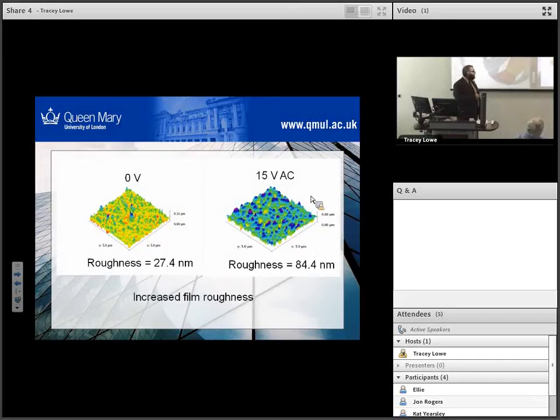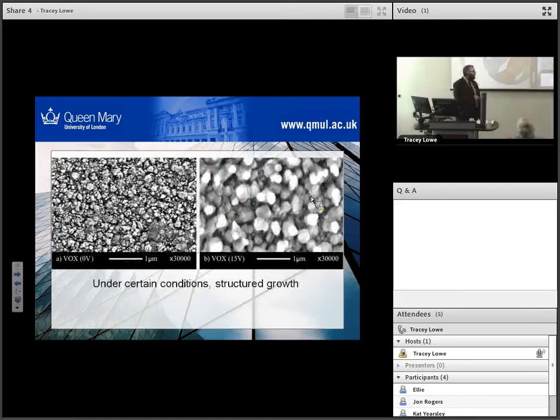Now this can lead to a massive increase in surface roughness. In this case, I think we've gone from about 28 nanometers RMS to 85, but I suspect that in the AFM the tip can't quite get down to the bottom of some of these features, so I imagine it's actually a lot more.